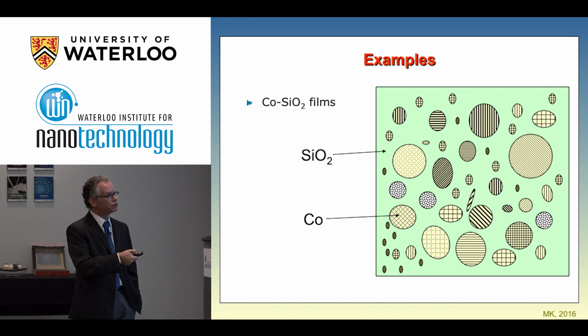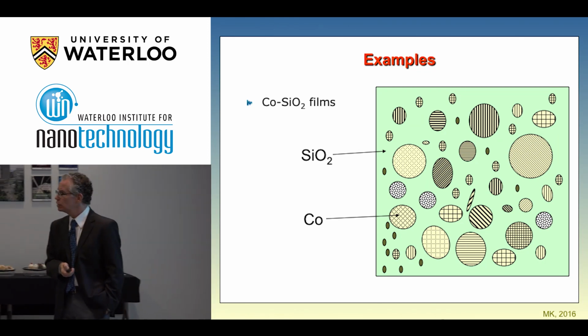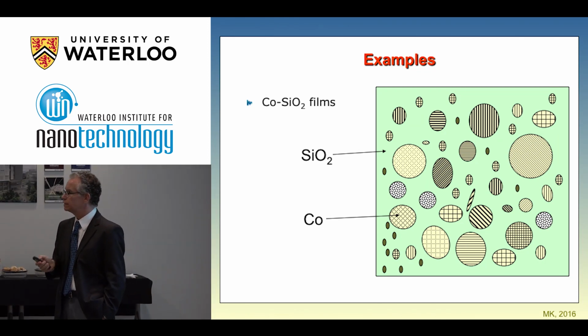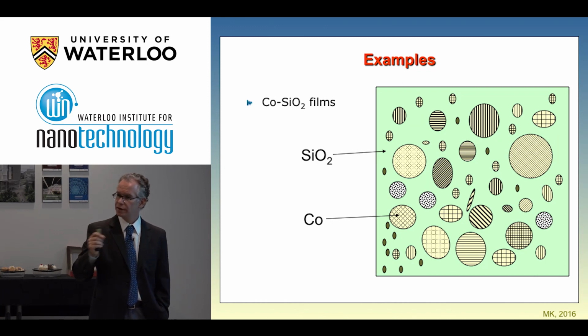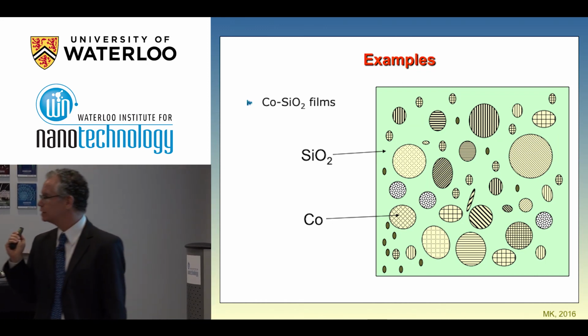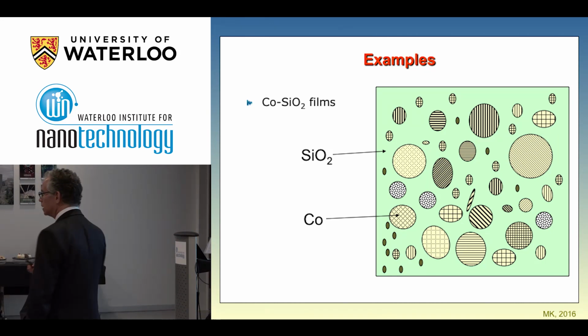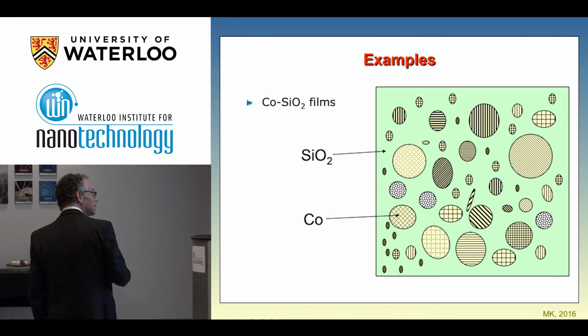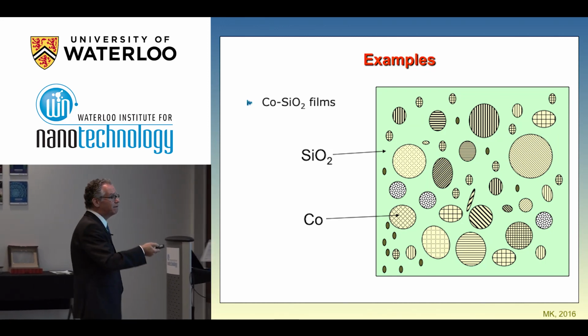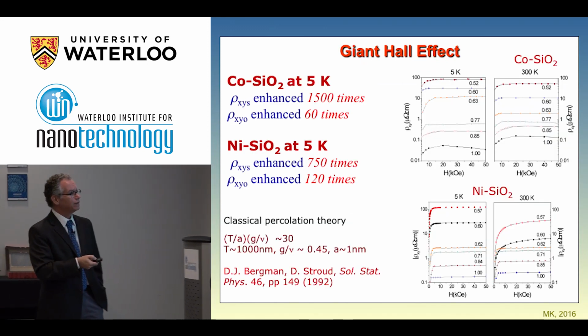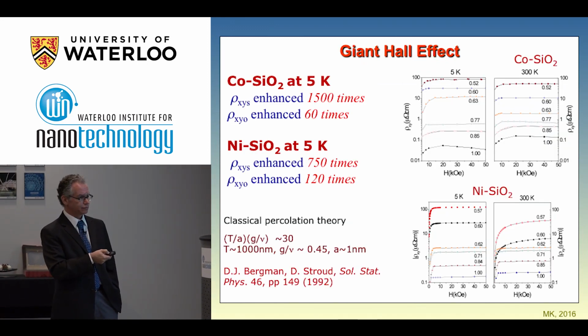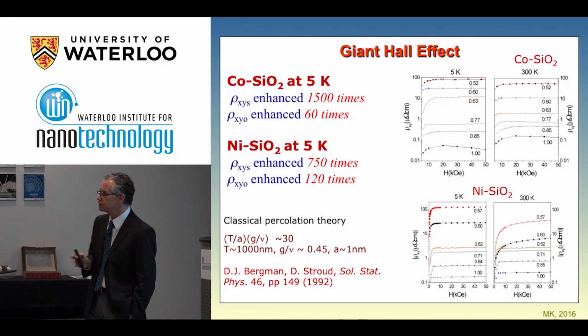Very similar to the previous one, we have cobalt, and we have here, as I mentioned before, silicon oxide. The only difference is that in the other one the matrix is metallic, and in this case, we have an insulator, and then we have a very interesting system. In this case, we can have a phenomenon which is completely open, yet nobody understands what is happening.